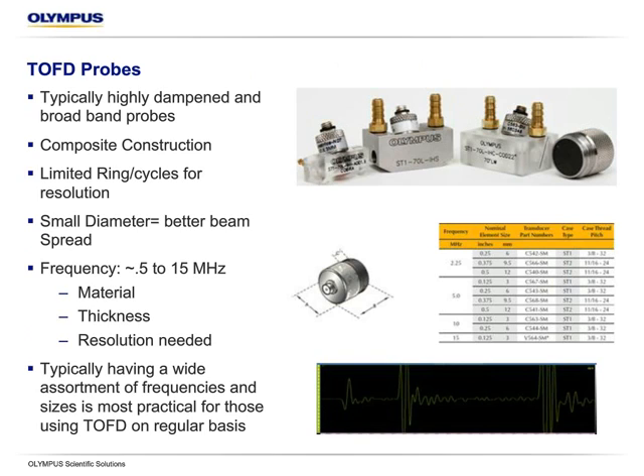So TOFD probes, typically composite material, also used in shear wave. You might have some of these for your typical conventional shear wave inspections. What we want to look for in TOFD is a high quality transducer because we want to limit the ring and the cycles for resolution. So if you look at the A-scan at the bottom, we want very clean peaks. We don't want a very broad signal. So when we highly dampen the probe, it basically makes a tight signal, and that allows us to accurately use the A-scan to do very precise measurements. If we had a very broad signal, our accuracy and thickness, our length and height measurement is going to be reduced. Just some things to consider.